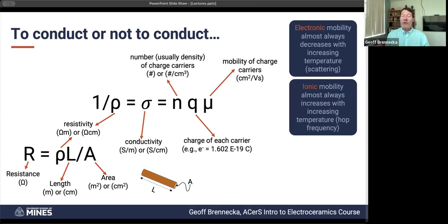How do you know which one is which? One possibility is you set up electrodes where lithium is not welcome, so lithium can't go through that certain electrode. It's called lithium blocking. And then you can say, all right, after I pile up lithiums against this barrier, anything else that gets through has got to be an electron.